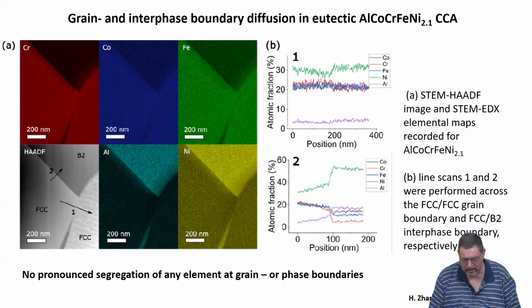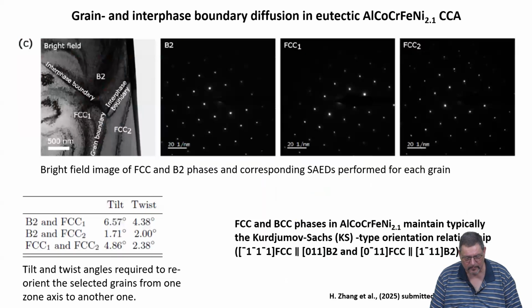Nice thing is we see that there is no pronounced segregation of any element at these grain boundaries as well as the phase boundaries. So that means for the later analysis, we can basically think of the factor S, the segregation factor, to be unity, and that will be simplifying things a lot.